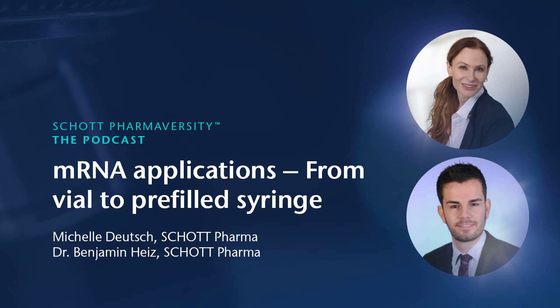Coming back to plunger movement, we conducted extensive testing using various syringe formats and plunger stoppers, varying different parameters. To complete our study, we also conducted transport simulations taking into account pressure drops that might occur during air freight transport. From those studies, we concluded that with the right choice of parameters, it is possible to minimize plunger movement and guarantee sterility. Additionally, despite the difference in thermal expansion coefficient between glass and rubber — on the order of two orders of magnitude — container closure integrity was demonstrated at minus 50 degrees Celsius using the CO2 headspace analysis method from Lighthouse.